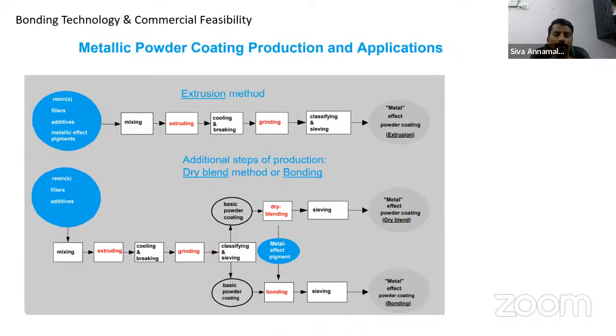The second one is called dry blending method. Dry blending method means you produce powder separately and you mix metallic pigment, preferably aluminum, into a blender, and you blend homogeneously, you supply. This is a good one. You will get very bright metallic effects, but the disadvantage is that the specific gravity, the density of metallic pigments, is much higher than the density of powder coating, almost 2 to 3 times. It means when you spray the powder at the time of application, powder and metallic particles do not always travel uniformly from the gun to the object. So the effect you get at your laboratory, the effect your customer gets at their line may not be the same. So customer needs to control their application condition to get the same effect as your master panel. This is the second method.